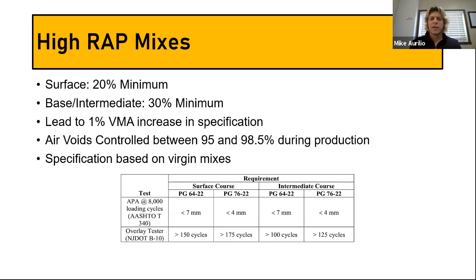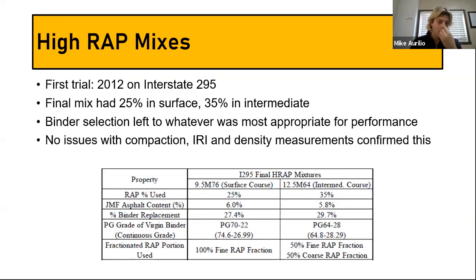All right, and that's the easiest way to do it, is to kind of just start with your virgin mixes and then slowly incorporate the RAP until you make the necessary adjustments until you reach the same level of performance on the tests you've chosen. So they performed a trial in 2012 on Interstate 295.